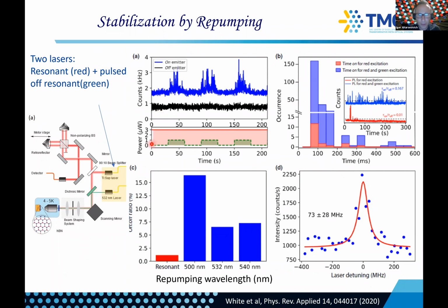And so you can see the effect here. So we're doing a pulse of green, and you can see that as we pulse the green, we can start seeing the emission occurring. So this is in addition to the resonantly excited laser. And as we turn the green off, we basically see just the background. And you can repeat it again and again. And you can also change your repumping wavelength to see what's the best one.